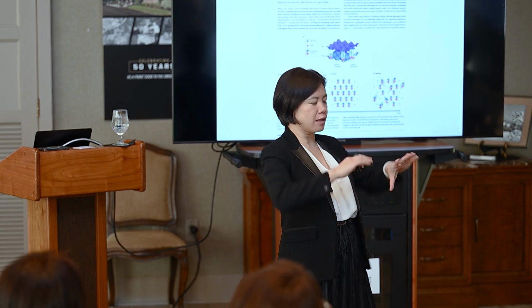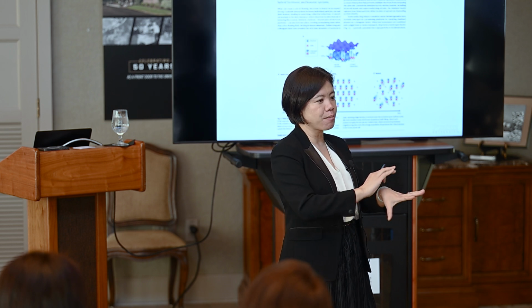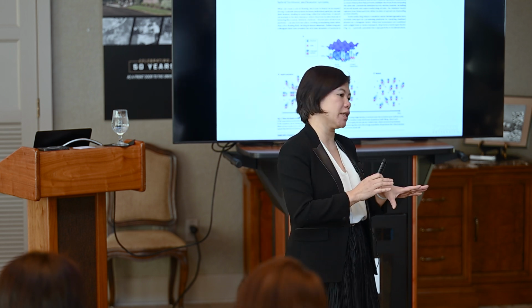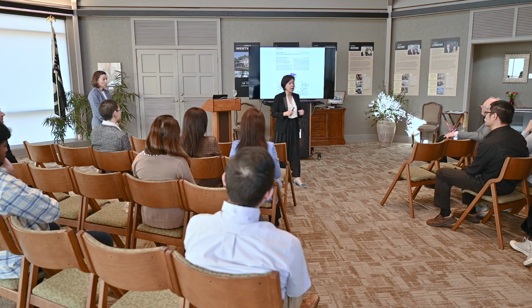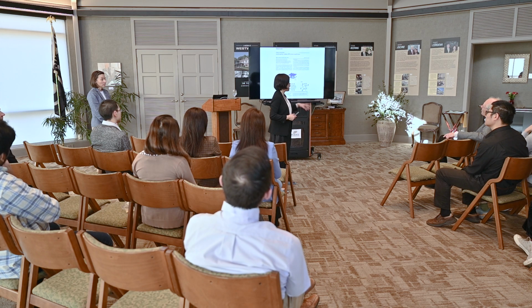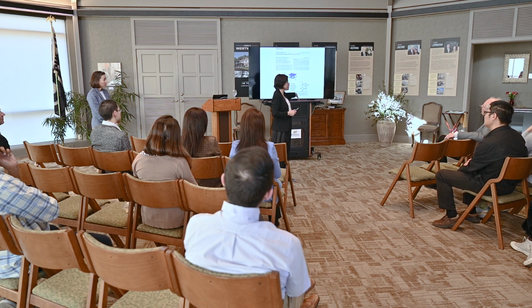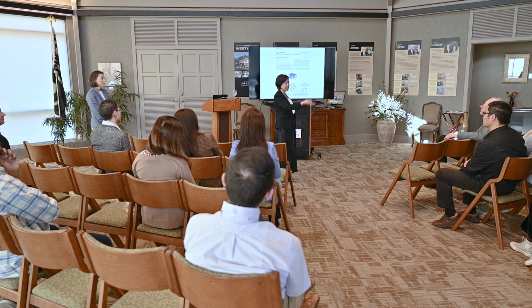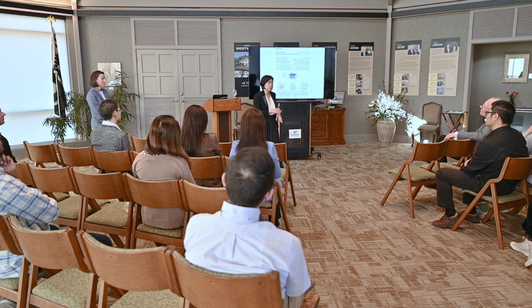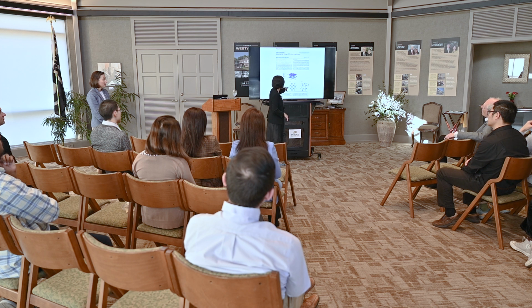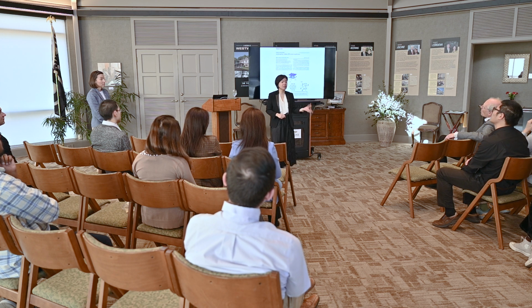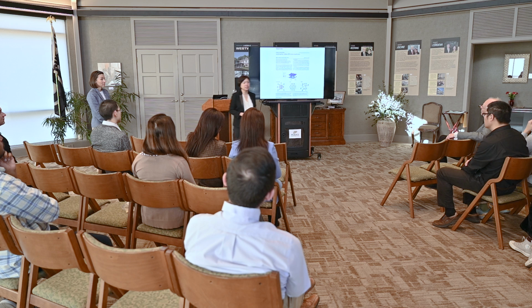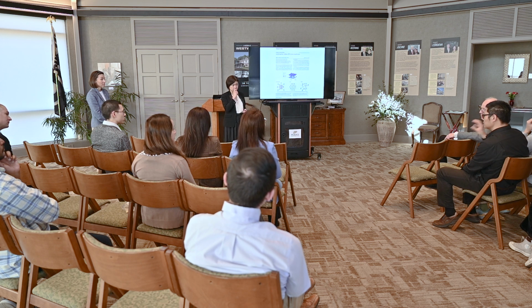Depending on the interaction, right? The beautiful thing about this twisted moiré type of system is that you can control the interaction to allow for different phases of matter. In this particular heterobilayer, no one has experimentally realized superconductivity yet, but in the twisted homobilayer, some of Yihang's work has actually shown superconductivity. In this case, it is the interaction between the exciton and the charges that would lead to superconductivity. But this is really low temperature superconductivity, right?